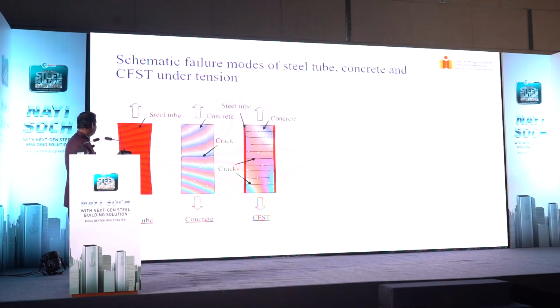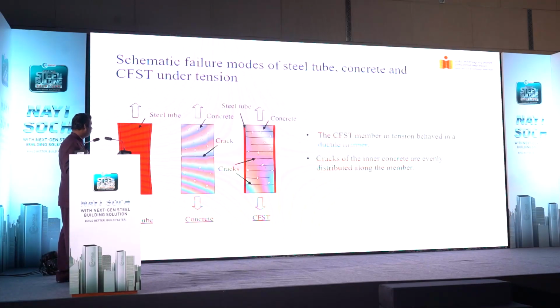And this again gives you, when it is subjected to tension, so it's a steel tube, and you have this crack happening here at the center, but it's a big crack. But when you fill it with concrete, you have micro cracks. So the member fails in a ductile manner. When the member fails in a ductile manner, it is a desirable failure mode.